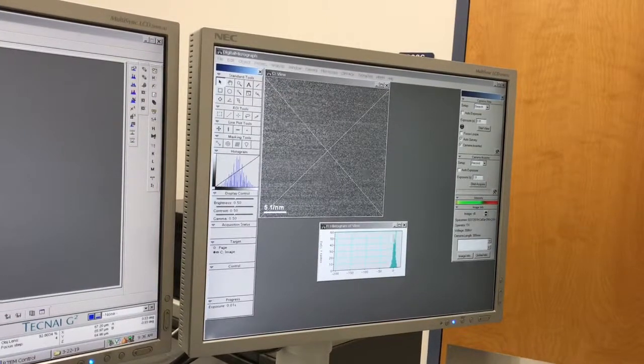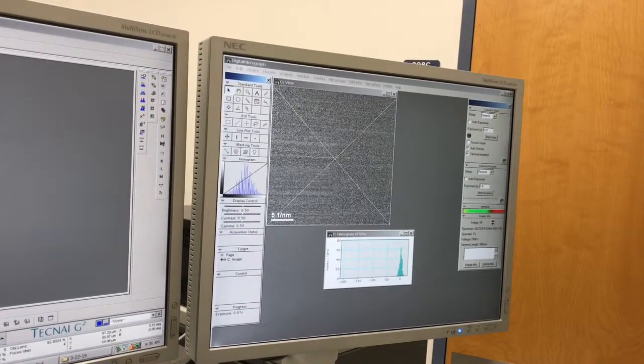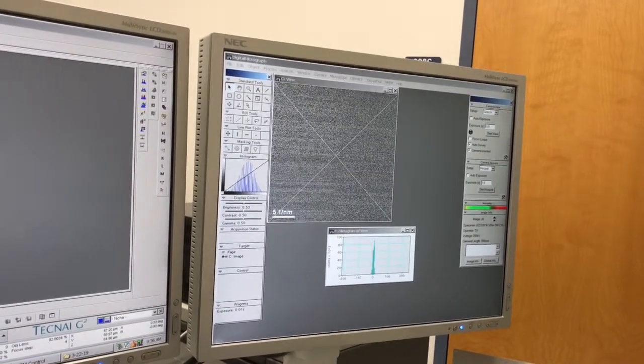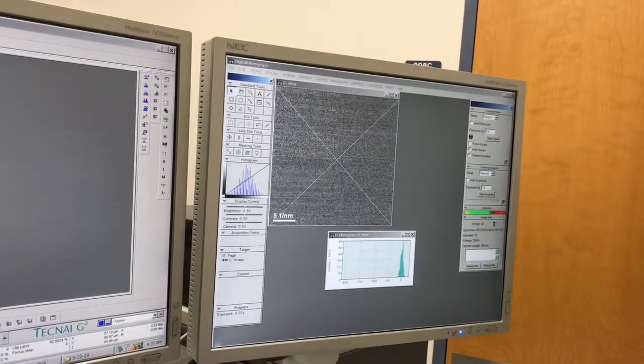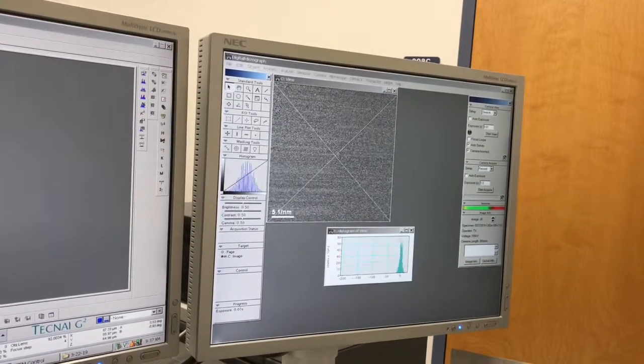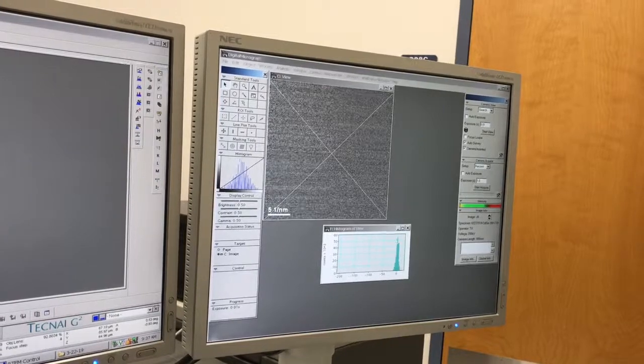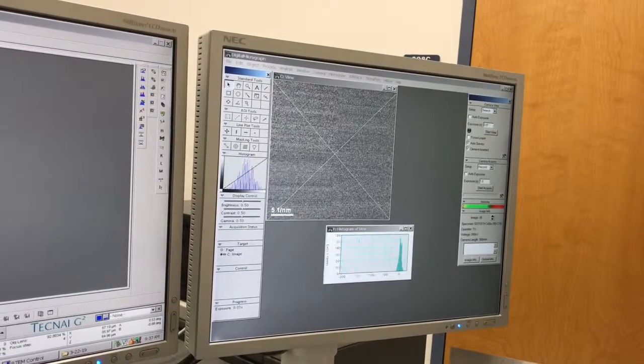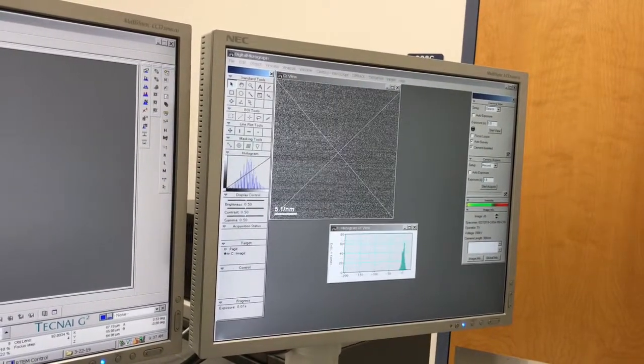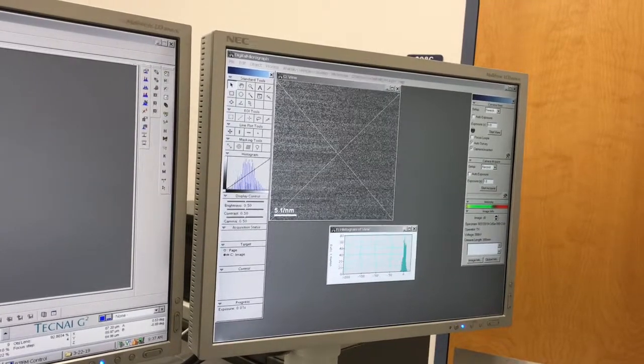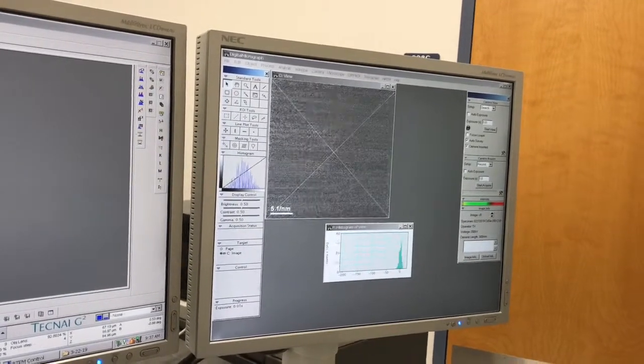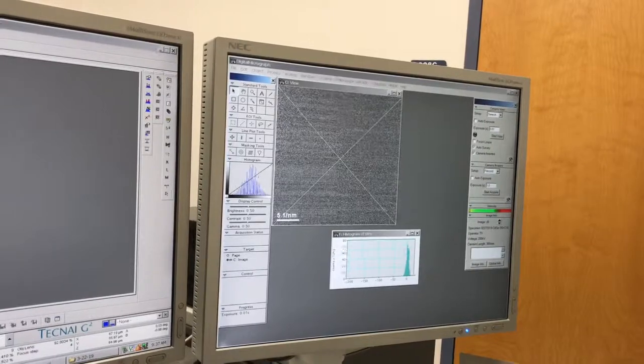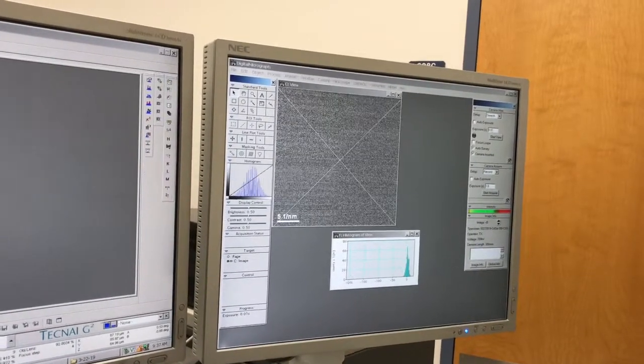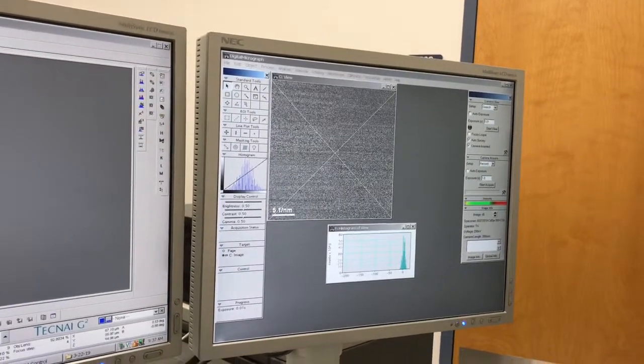When you're collecting a selected area diffraction pattern, particularly from a single crystal specimen, your overwhelming main priority has to be not overexposing the camera, not exceeding the dynamic range of the camera. It's very easy to do that when you're collecting diffraction patterns, because you are putting a lot of signal into really small areas, those focused spots in the DP.